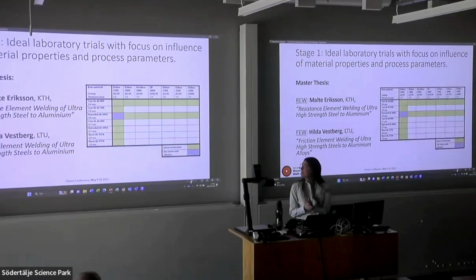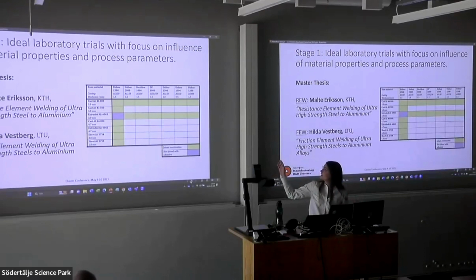Then just very, very briefly, stage 1 from the project. I mentioned we focused on the material properties. In this case, we of course had quite a large matrix containing a lot of different steels, a lot of different thicknesses, and then also some lightweight material. So both cast aluminium without heat treatment and cast aluminium with heat treatment, extruded aluminium and sheet aluminium.